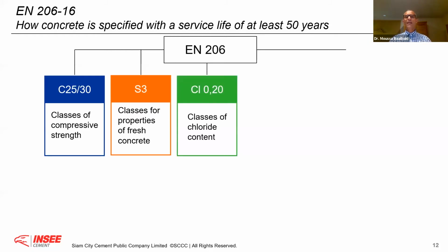The third one is the class of chloride. The class of chloride, because you can have a concrete exposed to chloride like marine, okay? It could be even not marine. You can use also chloride to melt the snow in the mountain, okay? This chloride can somehow, to a certain extent, have a certain negative impact on the corrosion. But at the same time, in your concrete, you have to also limit the amount of chloride. And we will see, for example, 0.1%, very often it is used, to 0.4, depending if the concrete is reinforced, if it is post-tension, therefore the class of chloride content is defined in the standard.